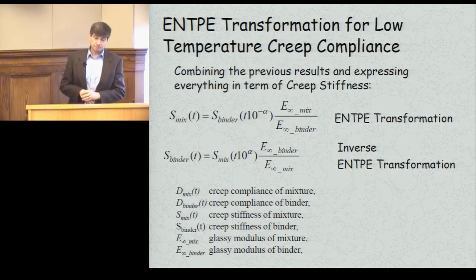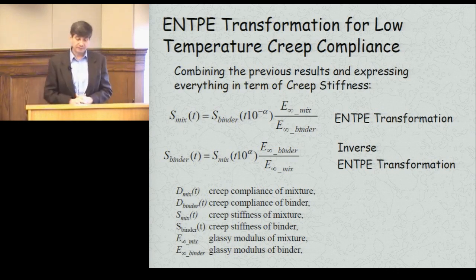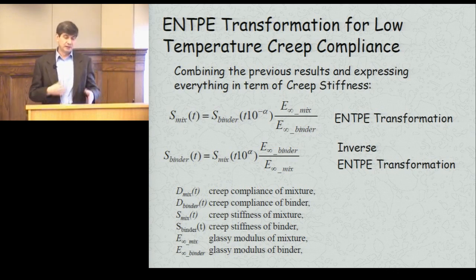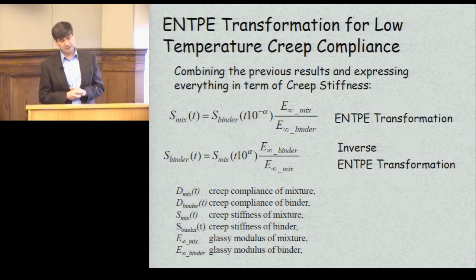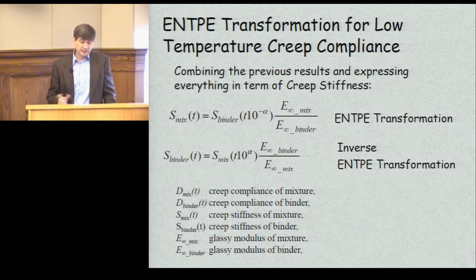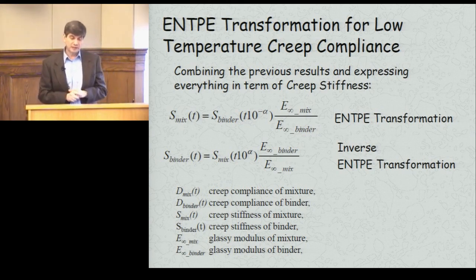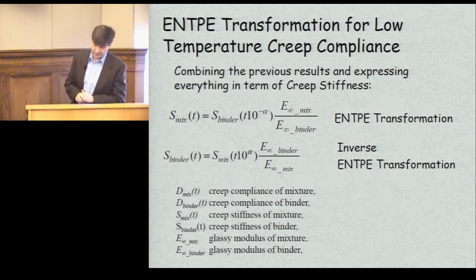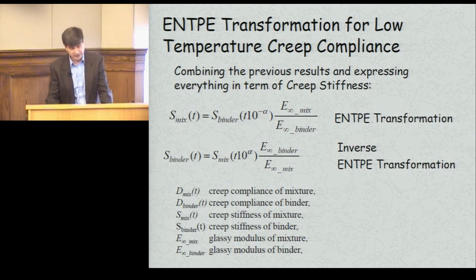Basically, it can be shown that the creep stiffness of the mixture is directly related to the creep stiffness of the binder, using some parameters that can be obtained from experimental work, which is actually quite important. This transformation, as we call it, is very easy to apply backwards, to solve the inverse problem, in which if you know the asphalt mixture property, in this case the creep stiffness, you can get the binder property. This is very important when dealing with mixtures that contain RAP, because it's a way to find out what the contribution of the asphalt binder in the mixture is. This is work under investigation, but it was very nice work, and we have been using it.